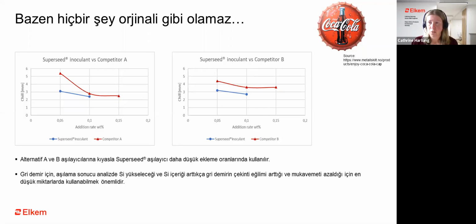In the right figure, we are looking at another inoculant. But here we can also see at 0.1 that there is a difference between superseed and this inoculant. Now, one way that a foundry can equalize differences in the performance of inoculants is to just increase the addition rate. So we have increased the addition rate for inoculant B, and we see that even at 0.15 addition, you cannot get to the same level as superseed at 0.1. And interestingly enough, even at 0.05, this superseed, which we know is a good inoculant and you can reduce it, behaves better than inoculant B in this case.